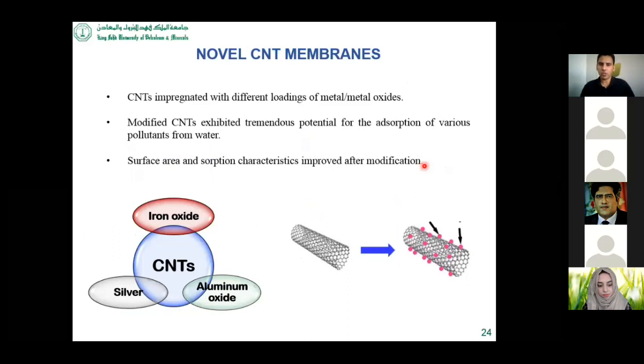Here I will share briefly our experience with the carbon nanotube membrane. We basically produce a novel class of the CNT membrane, different from what I mentioned earlier. What we did basically, we modified the surface of the carbon nanotube with various metal and metal oxide, for example, iron oxide, aluminum oxide, and silver. And then we employ these material in water treatment and batch experiment as adsorbent.